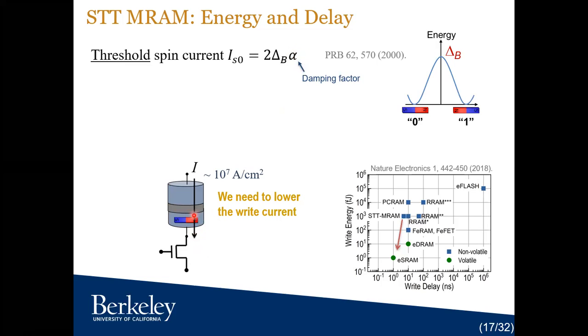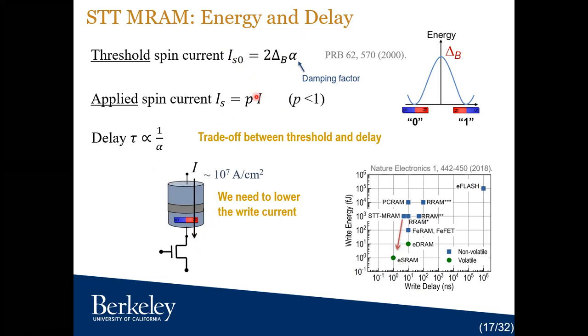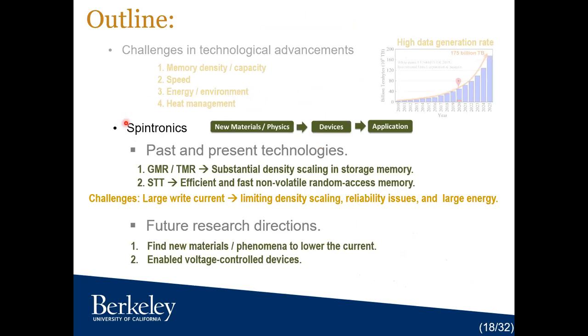It's a parameter that determines how your magnet switches. But as you lower the damping, your delay is inversely proportional to the damping. So if you try to lower your energy, you make the device slower. So there is a trade-off between threshold and delay. And in addition to that, to create a spin polarized current, we need to apply a charge current. And as I have mentioned, there is an efficiency factor, which is lower than 1. So you're losing something here as well. So that's why our write current is very high. So what we can do is try to find new materials and phenomena to lower the current, or try to come up with a new voltage control device.